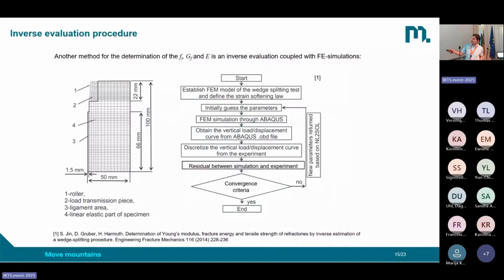We have our sample and produce a finite element model, for example, with the commercial software Abaqus. We have an initial guess of our parameters, do the simulations, and obtain the load displacement diagram. We then do a discretization of the load displacement curve and compare it with the experiment. Then we see how far we are, how close we are. We define a convergence criterion. If we do not fulfill it, we estimate with a solver a new parameter set and go to the simulations again, until we observe convergence and then have our results.